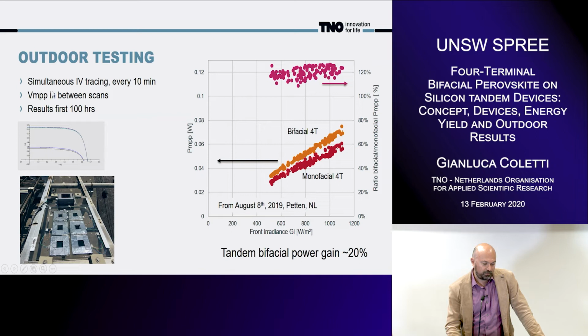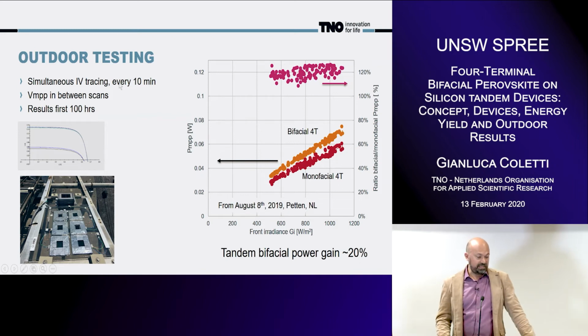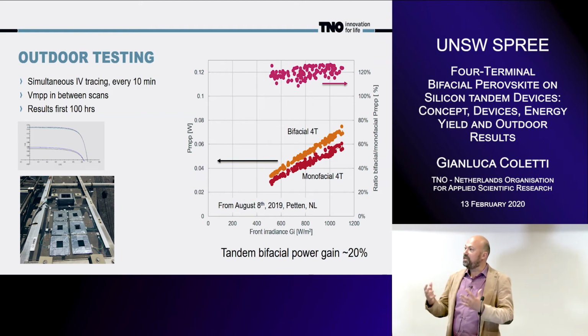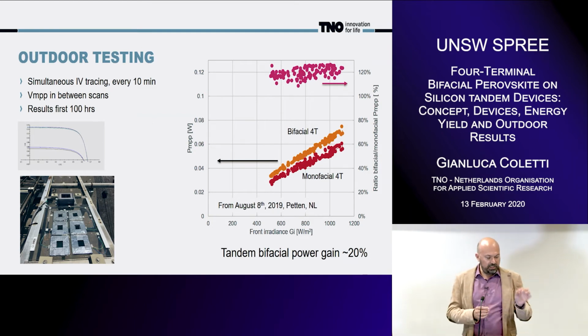This is something important when you do outdoor testing. We have a simultaneous IV tracing of all the modules at the same time. This is important because, especially in the Dutch climate where there are clouds that come and go, you really need to measure all under the same irradiance to easily compare the results, but that's valid everywhere. So essentially we simultaneously measure all the 6 modules every 10 minutes, and in between we keep all modules at the VMPP. The result that you see here, so you see the IV result, you see the first 100 hours